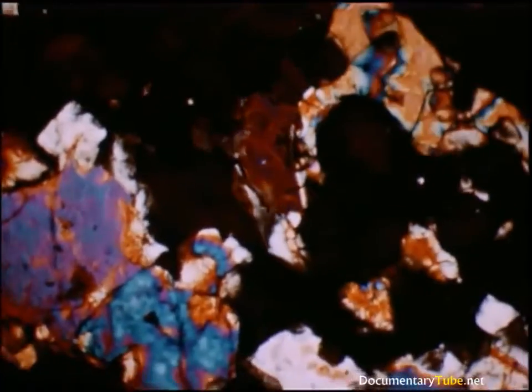Destructive chemicals react with or flux the brick material, causing them to lose their refractory structure. This microscopic thin section shows that geometric crystalline structure is still present in this Permanente brick after more than a year's severe service in a glass furnace. A section from a test brick of average bond and density shows the ravages of destructive fluxing, the loss of refractory structure, conversion of crystal to liquid, which gradually loosens and flushes away the brick structure. This brick saw the same service as the Permanente brick.